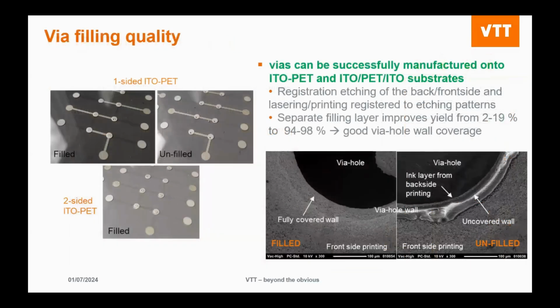So you can see a closer view of this, and basically, in the case of the ITO, the via filling step was quite important, so that you're able to get really nice contact between that thin oxide layer and the via hole.